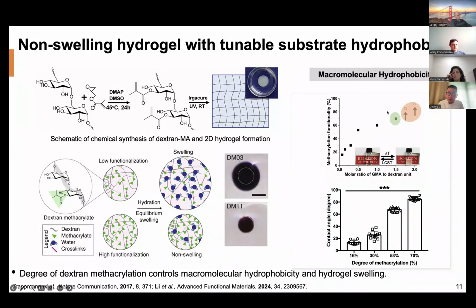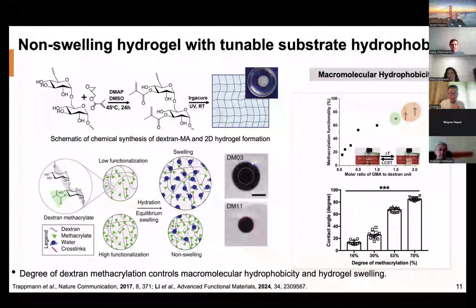To quantitatively characterize the swelling and hydrophobicity of the hydrogel, we use UV crosslinked hydrogels and contact angle to analyze how the contact angle relates to methacrylation. As you increase the degree of methacrylation, the contact angle gradually increases, and above 80 degrees we consider them hydrophobic hydrogels. The next thing we want to see is whether these highly hydrophobic hydrogel surfaces can absorb ECM proteins dissolved in PBS, showing non-specific adsorption that promotes cell adhesion.